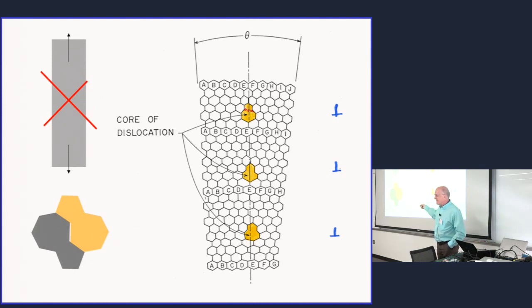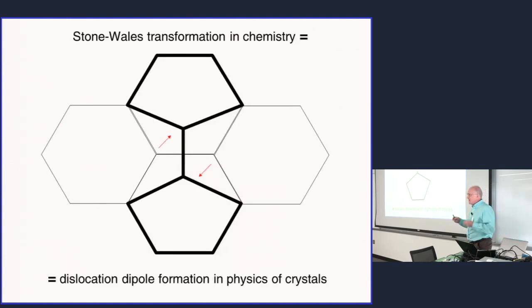And this should be the first defect, which is the topic of today's lecture. The first defect responsible for the yield in carbon lattice, in this two-dimensional carbon lattice. So how could it happen? And this is interesting because at that point you see a bridge here with fullerene chemistry. You can create this type of defect very easily, conceptually. You have a lot of hexagons. This is your wall of nanotube or graphene, many hexagons. All you need to do is take one bond here and rotate it 90 degrees. After that, atoms reconnect, and you have it, 5, 7, 7, 5, right?